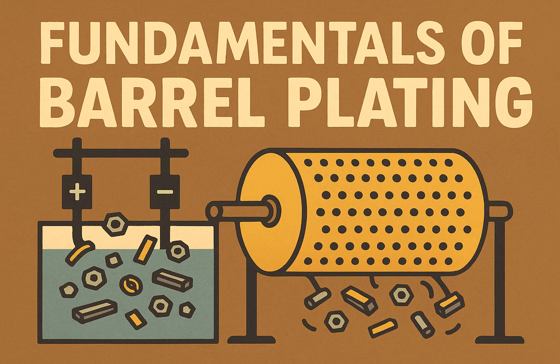And burning. What causes that? Coating burn, where the deposit looks dark, dull, or actually burnt, especially in high current density areas, can be caused by several factors. Insufficient boric acid, low concentration of the main metal salt, low bath temperature, too high current density for the bath chemistry, high pH, or insufficient agitation. Specifically, black burn in nickel plating is often attributed to a lack of sufficient boric acid. Adding boric acid to the bath is typically the fix. Boric acid seems important for nickel plating. It is, it acts as a buffer, and helps with brightness and preventing burn.